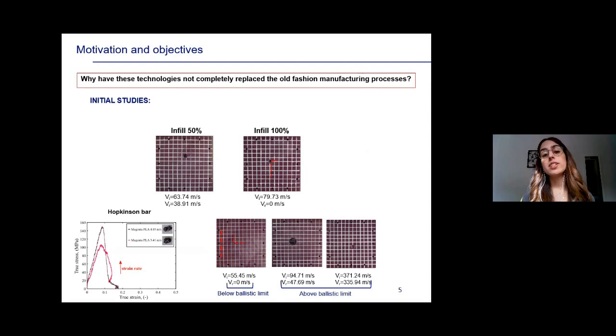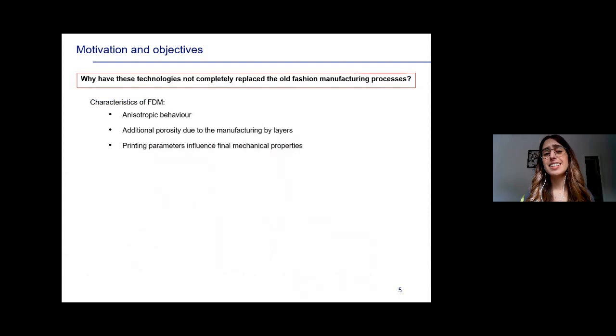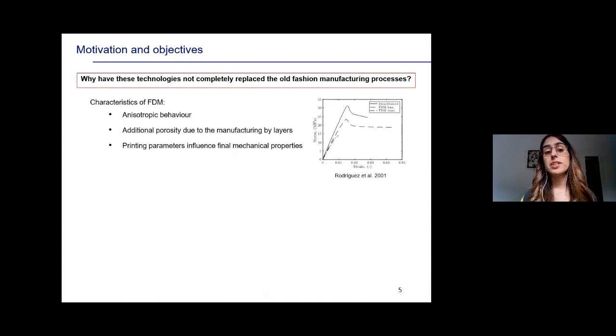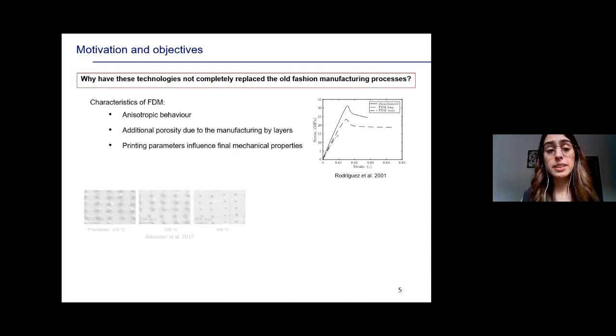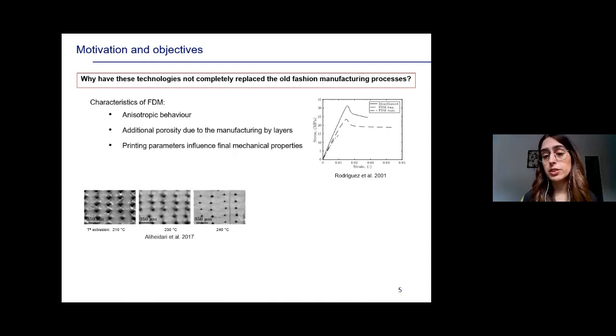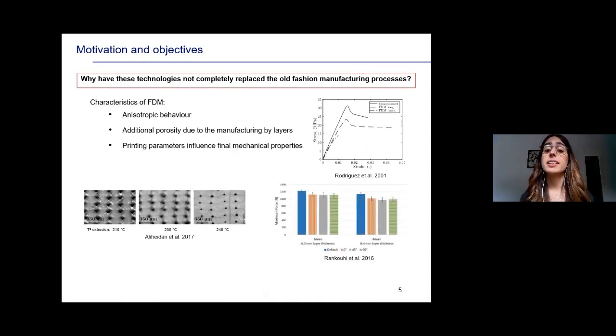produced. So the first thing that we did is that we went to the literature and we analyzed the characteristics of a specific additive manufacturing technology that is one of the most famous, that is fused deposition modeling. And we found that these components present an anisotropic behavior due to the direction of 3D printing, additional porosity due to the manufacturing by layers, and also that the mechanical properties of these components are influenced by the printing parameters. That means that depending on the printing parameters that we choose as a user, the mechanical properties are going to change.